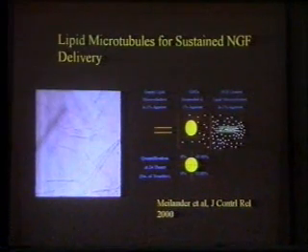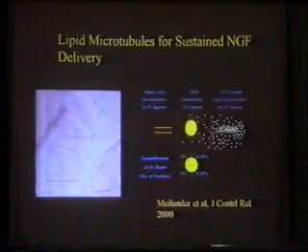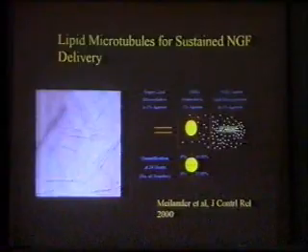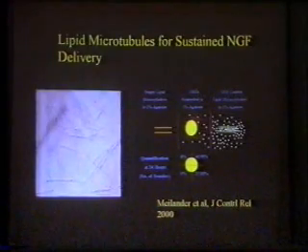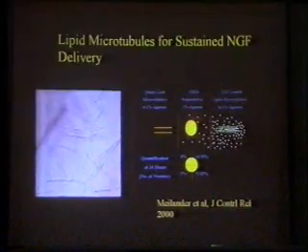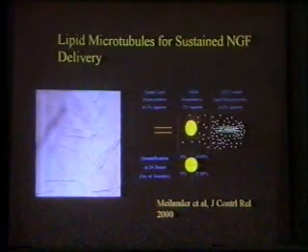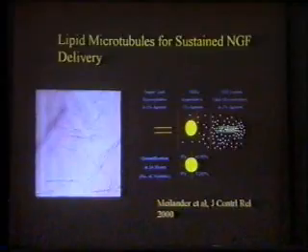And you can hydrate these straws with a concentrated solution of, we've done condensed DNA, we've done trophic factors, we've done different proteins of all different kinds, including siRNA. We've done all sorts of things with this technology. But essentially, they're empty straws. You take a concentrated solution. Through the capillary effect, you can load them up. You can centrifuge them down and wash off the external stuff.